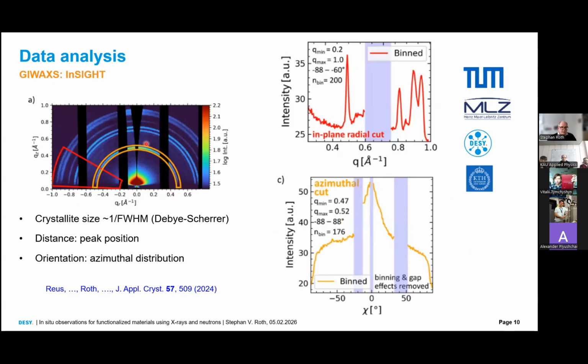We can make cuts along these peaks here. In this azimuthal cut, we can find out orientations, as I showed on the slide beforehand. When we make this pseudo-XRD cut, we get peaks which correspond to atomic distances. Then via the Debye-Scherrer equation, we can deduce the crystallite size, where the crystallite size is inversely proportional to the width of such a Bragg peak. This allows us to get out the interatomic or intermolecular distances, the sizes, and the orientation of the crystallites. And we have developed together with TU Munich a program for this.